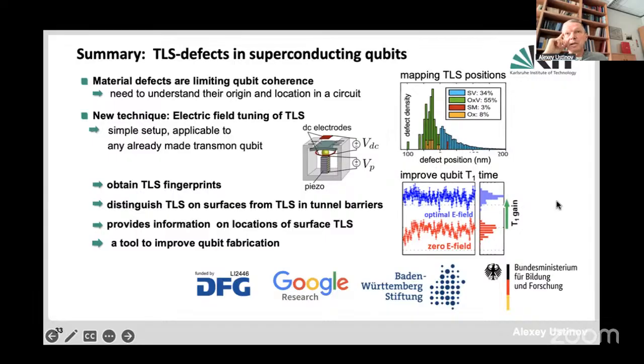The problem is that the quality of the junction needs to be high, and the best quality tunnel barrier, which has been found over many years, is aluminum oxide, which is grown on pure aluminum. If you make epitaxial aluminum and grow this oxide on epitaxial aluminum, it gets a little bit better, but not very much, not significantly really to motivate going to epitaxial growth, which is of course much more complicated. So using different superconductors, as you said, or using passivation techniques will probably be a solution, but this is a long process which already is going on for quite some time.